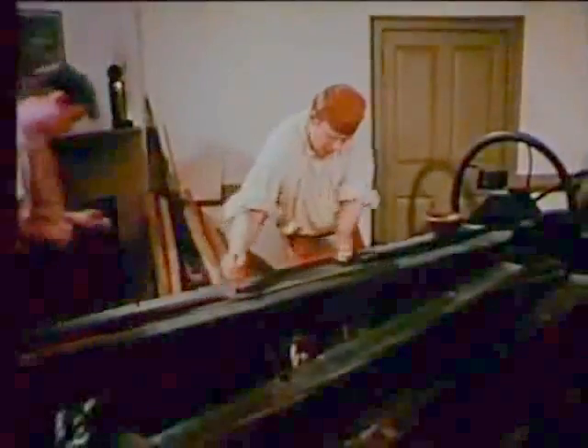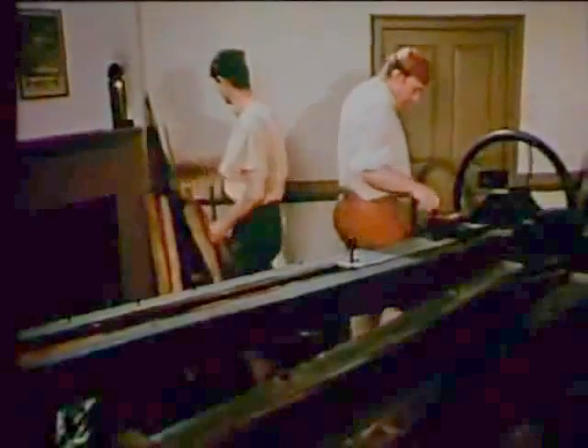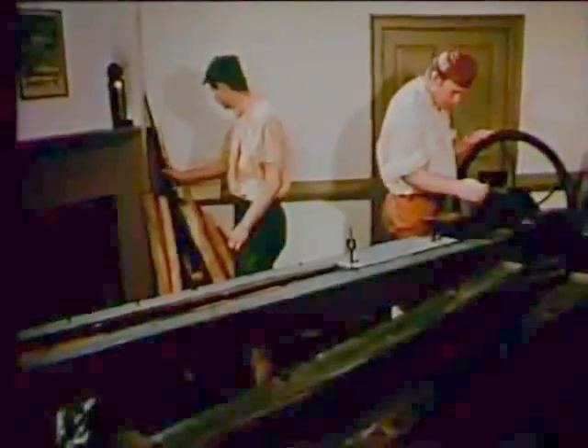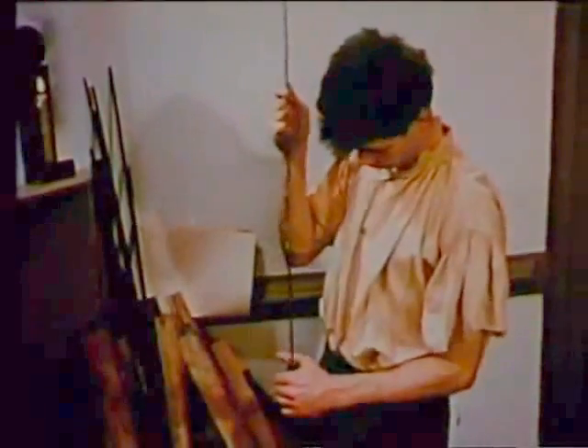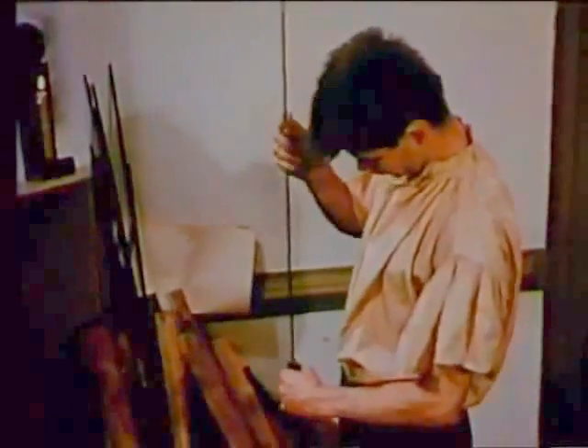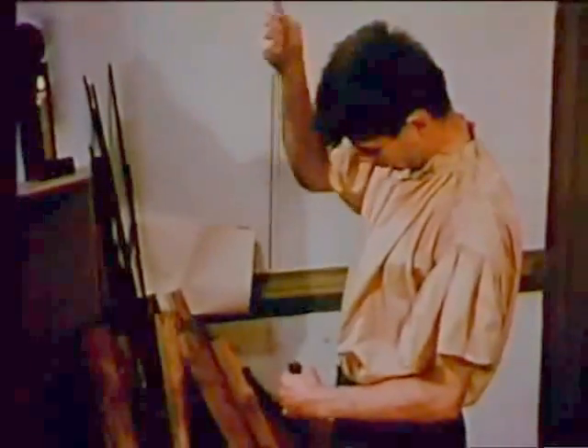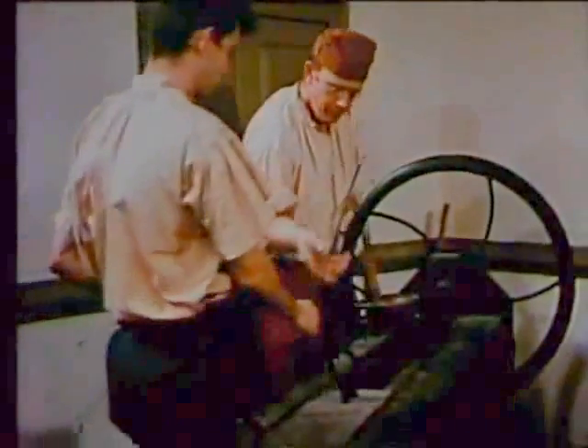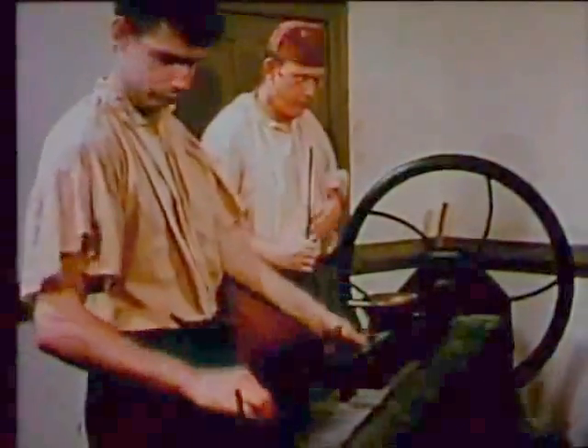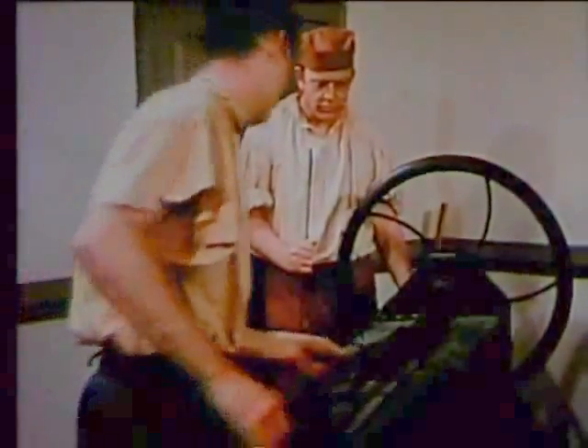The perfect gun barrel is a smooth, straight tube. It should be nicely finished on the outside, have an even wall thickness, and be as polished as possible on the inside. The objective of the boring operation is to produce a straight, smooth hole of the proper size. The boring operation itself is quite simple. The barrel is mounted in a sliding carriage. It is lined up with a chuck and held in place with wooden wedges.